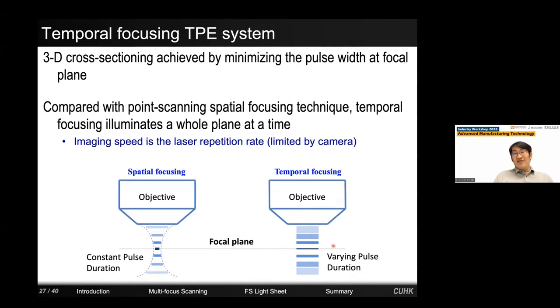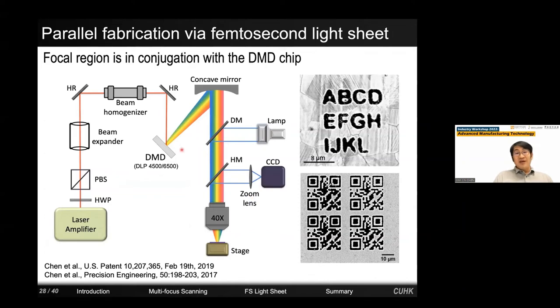This idea was actually not invented by our group, but by some microscopists in 2005. In order to use this for fabrication, we have to generate specific patterns on the light sheet. So that's where our contribution came in. We replaced the optical grating with a digital micromirror device. As I said, a DMD is a blazed grating with an angle of 12 degrees. So by selecting the proper diffraction order in an experiment, the minus fifth order diffraction, we can achieve a high laser efficiency of around 50% and implement temporal focusing. As a result, the DMD surface and the work plane are in conjugation, so whichever pattern is displayed on the DMD will be displayed here.